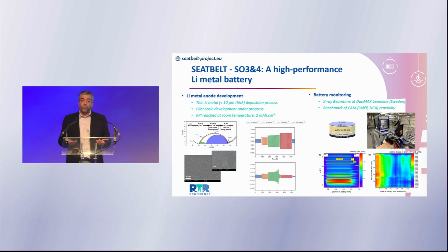And this helps us to play with either the rugosity, the thickness of the lithium metal, or any porosity effect, etc. And using some electrochemical methodology, we found out now that we are capable to process 10 micrometer thick lithium metal with correct cyclability. And what is interesting, in our recent development, we reach one of the KPIs of the project, because at room temperature, we reach a cyclability capacity of 2 milliamp hours per square centimeter.